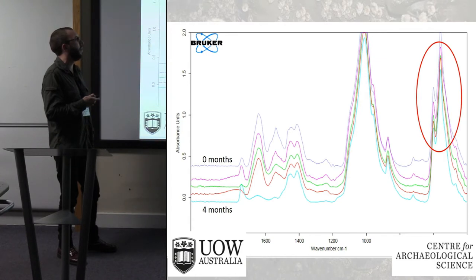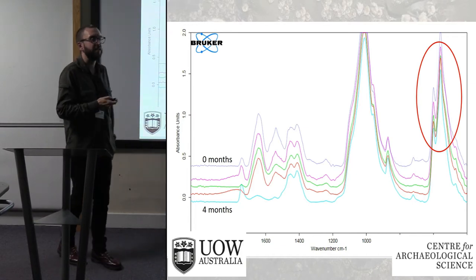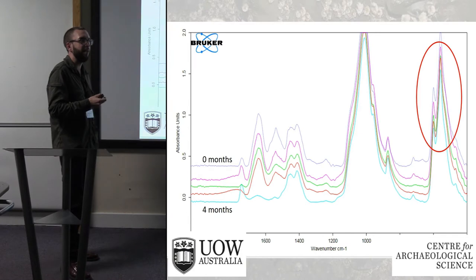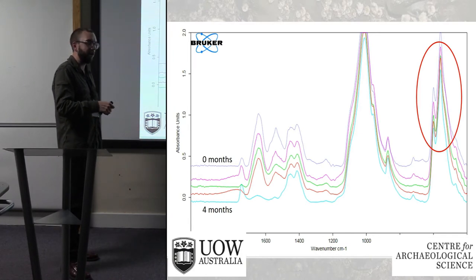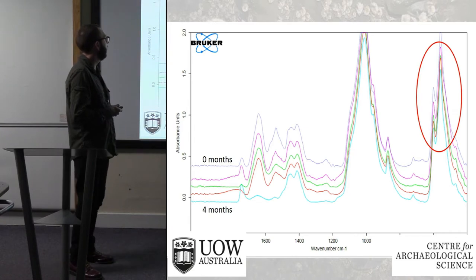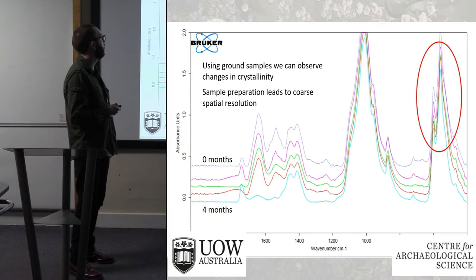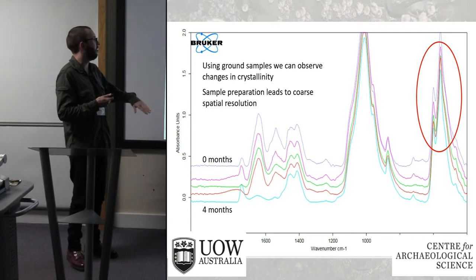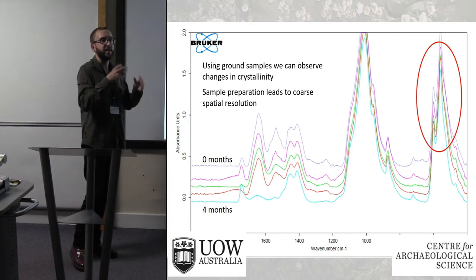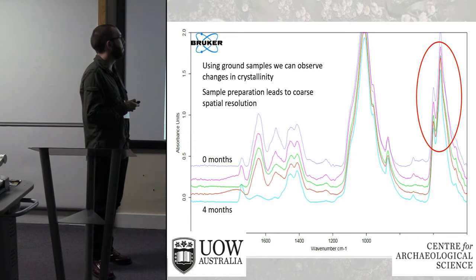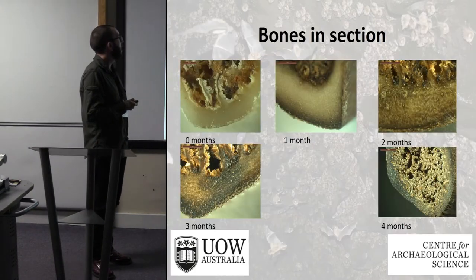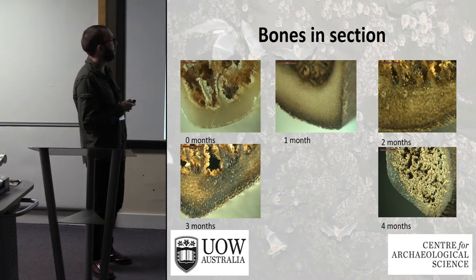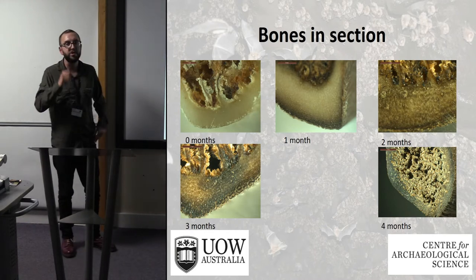The powder ATR-FTIR gives much more range and better data in that sense, but it's not very spatially resolved — we have to crush off parts of the bone, so sampling isn't ideal. We have a tentative correlation between decreasing collagen in the outer layer and increasing crystallinity as the phosphate minerals reorder, but it's not well spatially resolved.